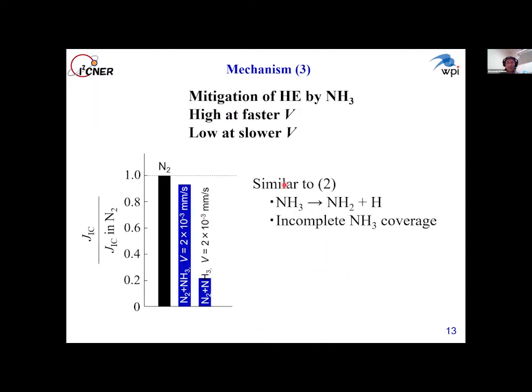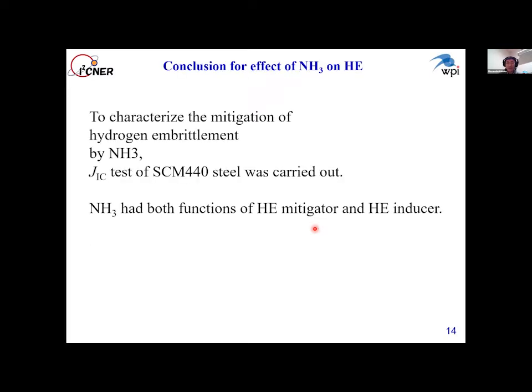Regarding the mechanism that mitigation of hydrogen embrittlement by NH3 was reduced at lower loading rate, a similar mechanism, NH3 decomposition and incomplete NH3 coverage, can be considered. Conclusion: to characterize the mitigation of hydrogen embrittlement by NH3, fracture toughness test of SCM440 steel was carried out. NH3 had both functions of hydrogen embrittlement mitigator and hydrogen embrittlement inducer.